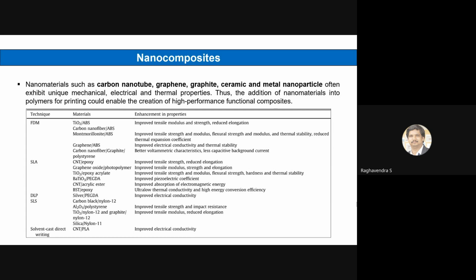Similarly, in terms of SLA, you can see some photopolymer added with CNT, graphene oxide, and acrylic ester and CNT, where you can get improved piezoelectric coefficient, tensile strength, modulus, and flexural strength. Similarly in DLP and SLS.